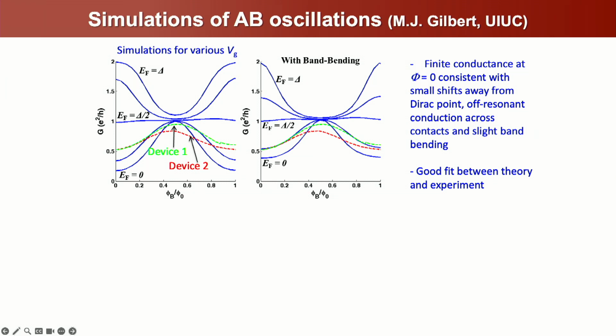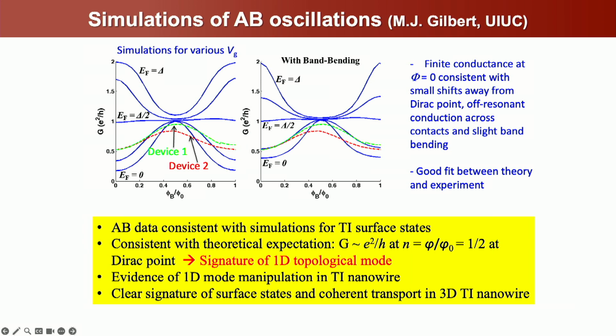And again, how do you characterize these surface states? Well, you can show that at least you get something that's consistent with theoretical expectations, that you do have evidence of 1D mode manipulation, and that you wouldn't get any signatures at all if you didn't have surface states and coherent 3D transport. Okay, so now we can show that at least these basic qualities of the topological materials are there and are reasonable, and you can measure them in transport.